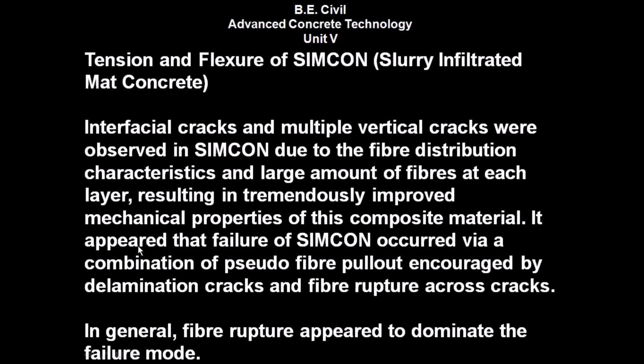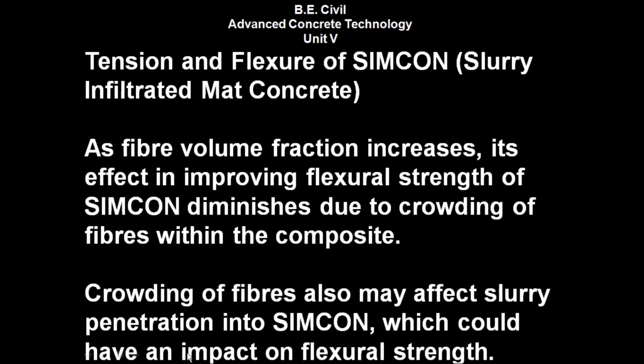It appeared that failure of SIMCON, that is slurry infiltrated mat concrete, occurred via a combination of pseudo fiber pullout encouraged by delamination cracks and fiber rupture across the crack. In general, fiber rupture appeared to dominate the failure mode.